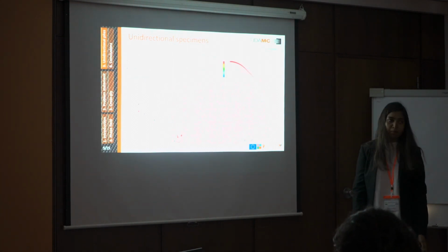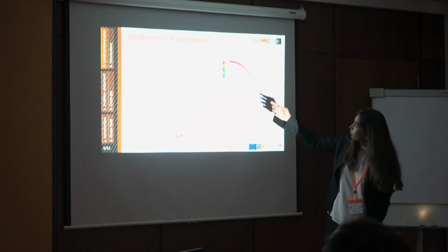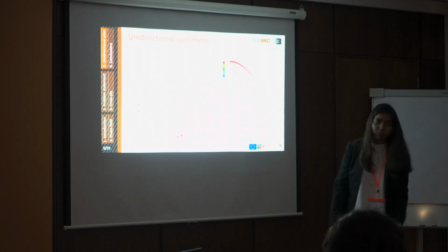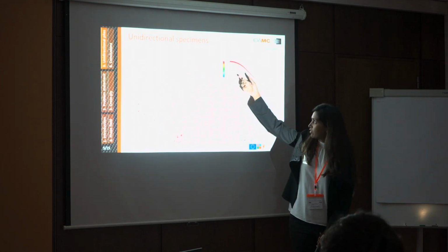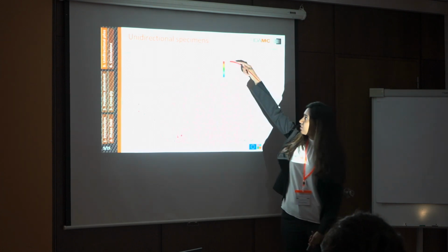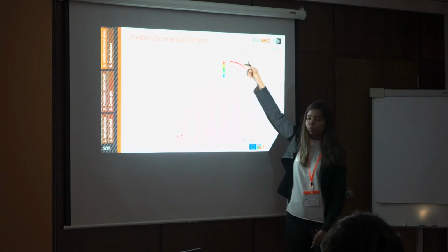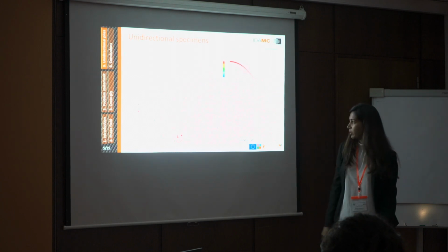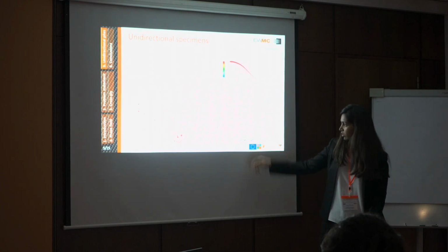So when we look at the damage, the state variable is a parameter which represents the resisting damage. It's not clear, I'm sorry. 0 indicates no damage, 1 is a complete damage. We can see that the delamination starts in the center in the mid-radii section and it propagates until the end of the specimen. This is a moment versus rotation curve.